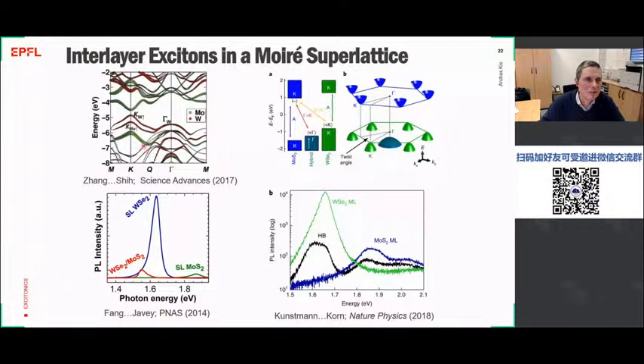So if you just looked at the band structure of a heterostructure composed of molybdenum disulfide and tungsten diselenide, then this would be the energy which would correspond to the direct K to K transition. But in this system, at room temperature or more than cryogenic temperatures, we also have the possibility of these momentum indirect transitions between the gamma point in tungsten diselenide and the K point in MoS2. And then if you look at the energy difference, it's pretty much going to correspond to what we see in photoluminescence. So we see roughly these energy peaks in photoluminescence around 1.5 or a little bit more electron volts, which can be explained by this energy difference between the gamma and the K point. So this means that the dynamics of excitons is a little bit more tricky to understand than what you would usually expect from just a simple picture of band alignment.